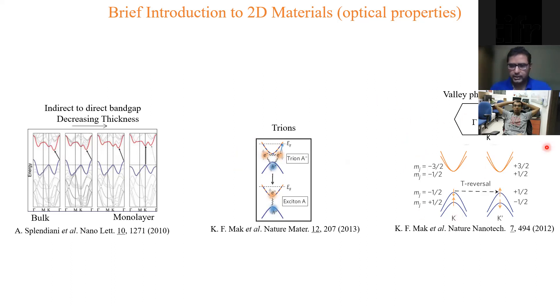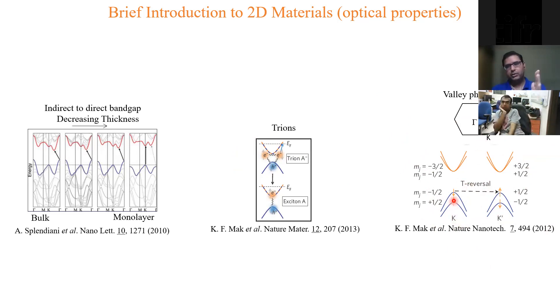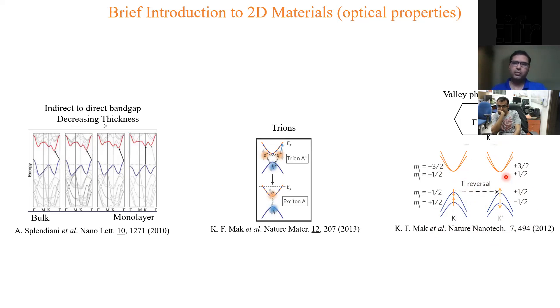Because of a combination of broken inversion symmetry and time reversal symmetry, these materials have a typical band structure around the K point where you can selectively excite one of two alternate valleys at K and K' points. For example, using right-hand circularly polarized light you can excite only the K' valley. When electrons and holes excited at K' recombine, they preserve this circular polarization, so the emission is also circularly polarized, which is typically seen in experiments.